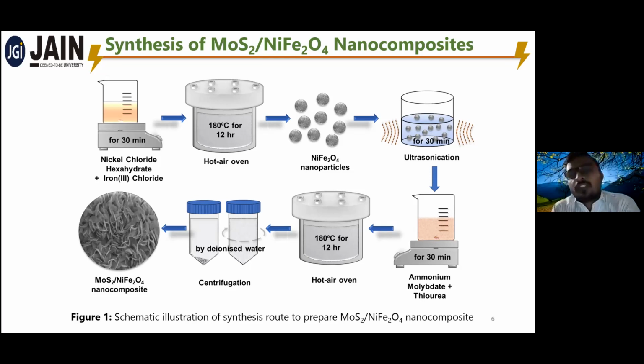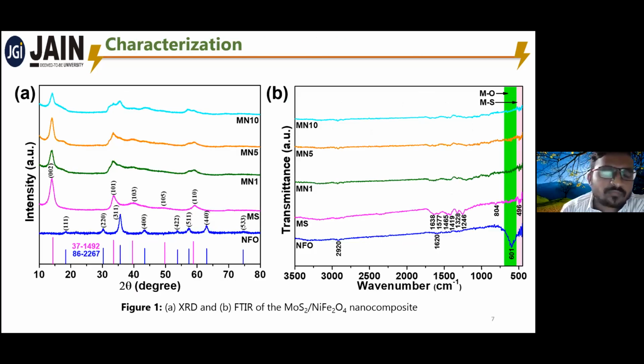We are also interested in optimizing the concentration of the nickel ferrite. We change the concentration of these nickel ferrite nanoparticles to 1 mg, 5 mg, and 10 mg, and then we judge the performance of all these synthesized catalysts for supercapacitor and water splitting applications. These are the XRD and FTIR graphs of the MoS2 NiFe2O4 nanocomposite.